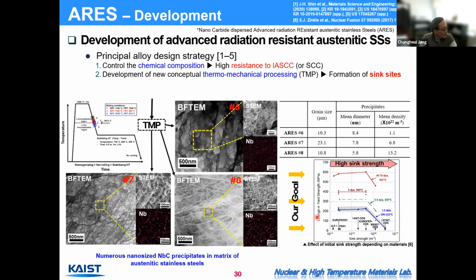So our idea is that we try to precipitate a huge number of nanosized carbide within the matrix by properly controlling the composition and some mechanical processing, and that provides a significant amount of sink sites, so we can have swelling resistance and irradiation embrittlement resistance.